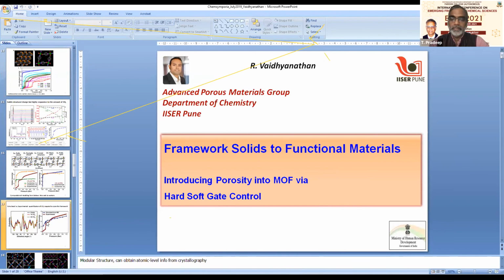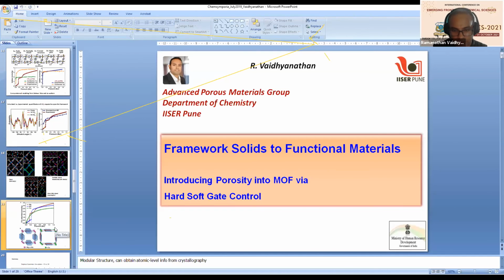That is what the molecular dynamics calculations are telling us. Though we are arresting at a given point, a specific orientation of the pyridine rings, for example, in reality the whole study shows that what actually simulates the experimental isotherm is a mixture of these configurations, not just one specific configuration. This is with respect to the ligand. In the same way, in the case of the iron, the magnetism study as well as the XPS clearly points out that there is a slight contribution of Fe2+ also in the structure, which means though I have given a formula as FePYC.OH, there is a variation in the amount of OH rather than a fixed formula. So both ligand as well as metal sites can have a mixed configuration. I totally agree with you on that.